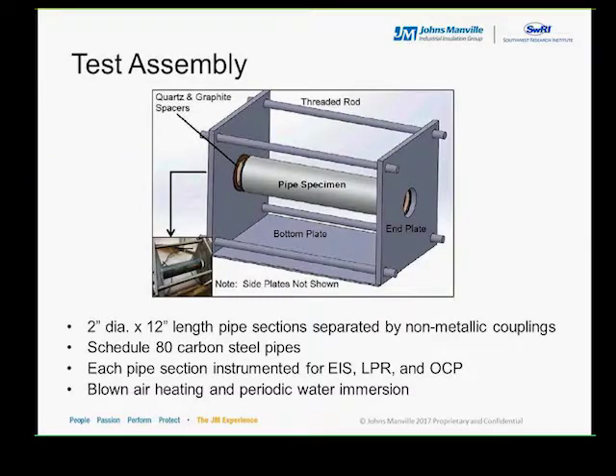The NACE TG516 test protocol uses coated or uncoated pipe spools that are insulated and placed horizontally in a vessel that contains the electrolyte. To simulate and accelerate the breakdown of the insulation systems, holes are drilled on the bottom of the insulation jacketing. The test method permits various CUI environments that range from isothermal to cyclic operation.